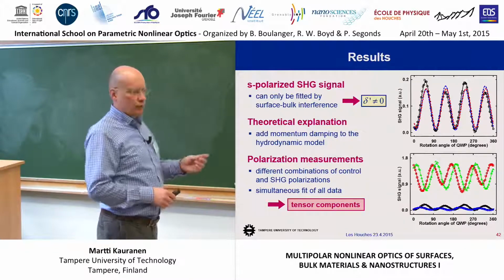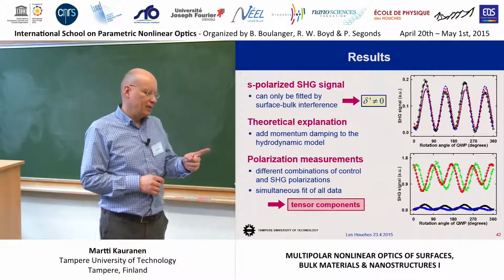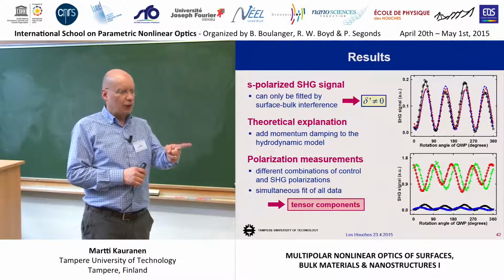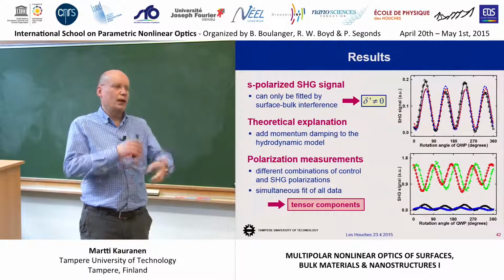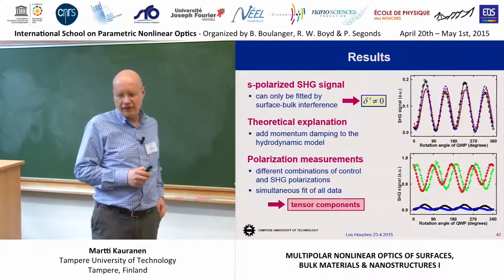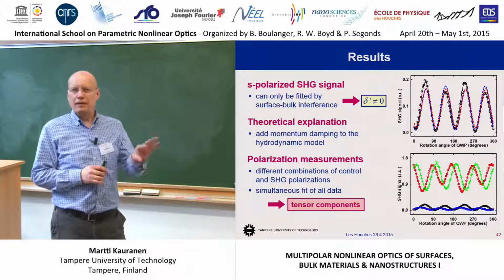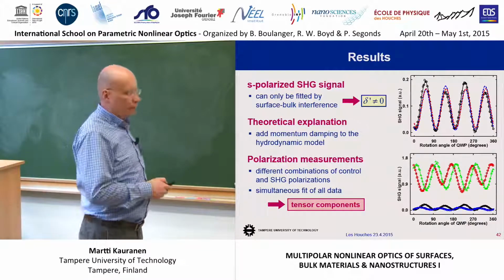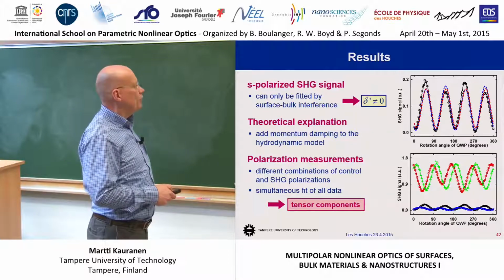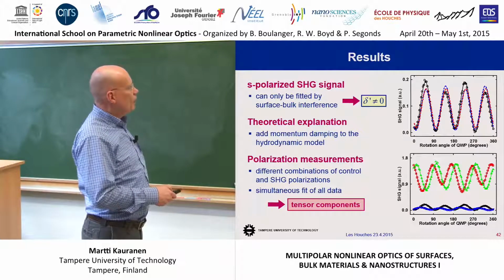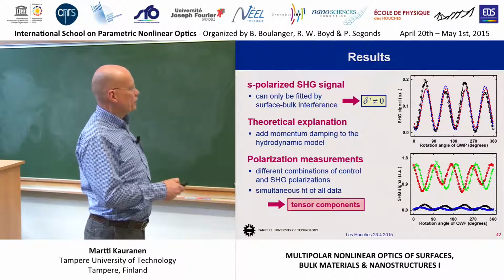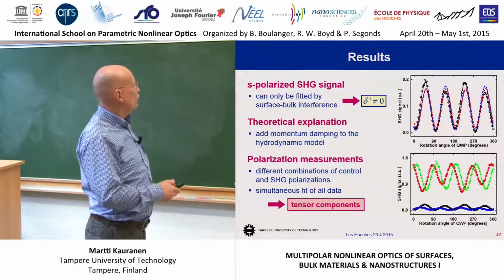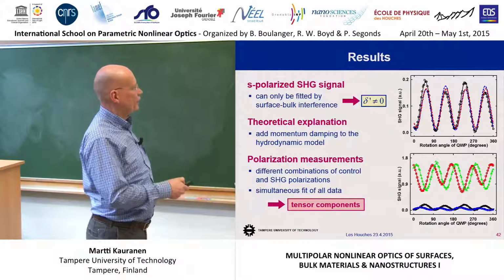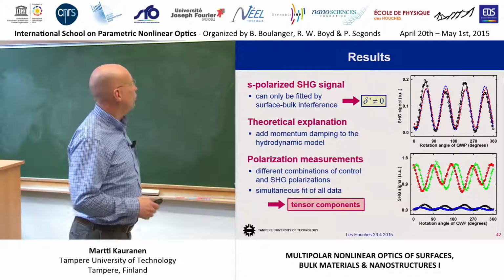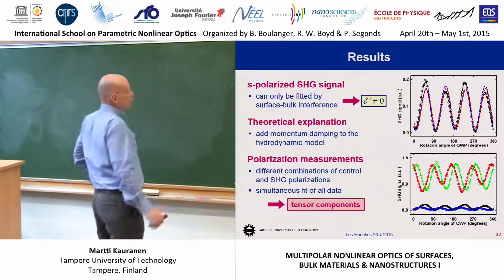The difference being whether we use, when you do surface nonlinear optics, you can define the response in terms of the fields outside of the medium or inside the medium, or some combination. And then you get slight differences from the transmission coefficients and things like that. And we took into account both possibilities. And what we can predict using the surface response also is indeed the blue and red dotted lines here. No good match. Then when we take into account surface bulk interference, we get a very nice fit to the data. Okay, so delta prime seems to be non-vanishing.